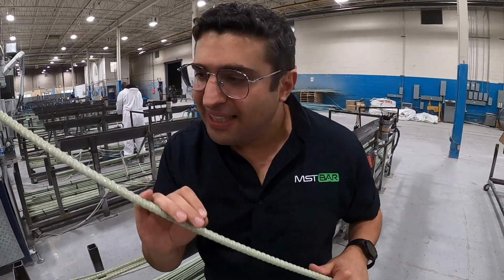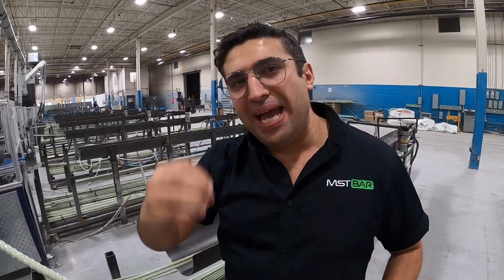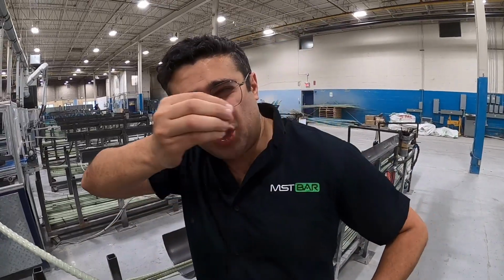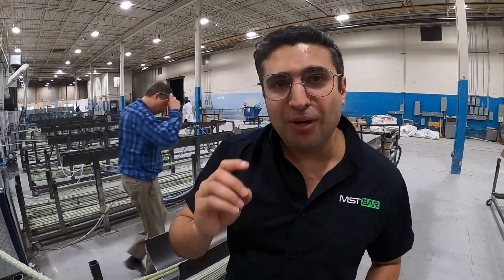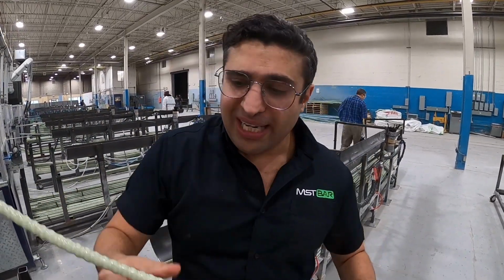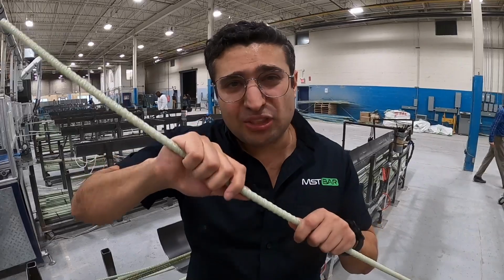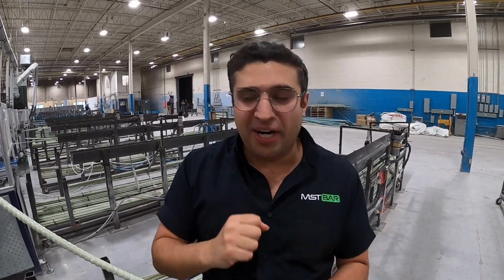The key here, Matt, is for these fibers to be perfectly packed and fit into a very tight mold to make these fibers that I showed you extremely straight, packed properly together to make this part. While we are doing this, we have to ensure that this rib on the bar, because these ribs are everything to adhere to the concrete. That's the key element for our bar. You can have the strongest rebar in the world, the strongest concrete, but if these two don't bond together, it does not work. And these ribs on the surface of the bar are everything.